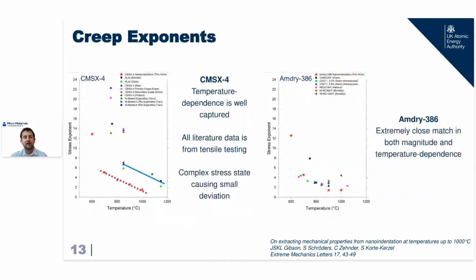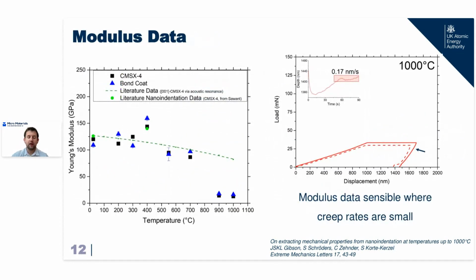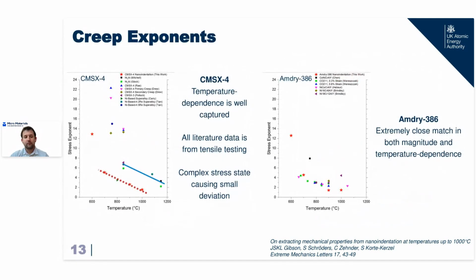So that explains why the 900 and 1000 degrees are a bit low. We're measuring a creep effect. We're not having that elastic unloading that we need for reliable measurements of modulus. We can also fit to that hold segment in the middle and hopefully extract something with creep.